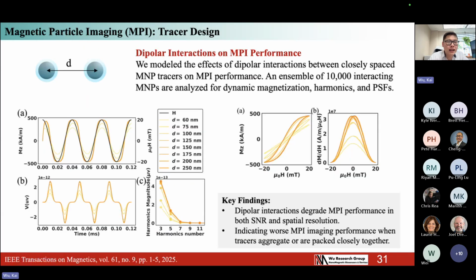Lastly, I think this will be the last part. We consider the dipolar interaction, which is a very popular consideration in industry and biomedical application areas. If the particles are too dense to each other, they will interact with each other. So we consider this dipolar interaction of particles, and we vary the interparticle distance from small distance, very high dipolar interaction, to the large distance, no dipolar interaction at all, with this 250 nanometer distance.